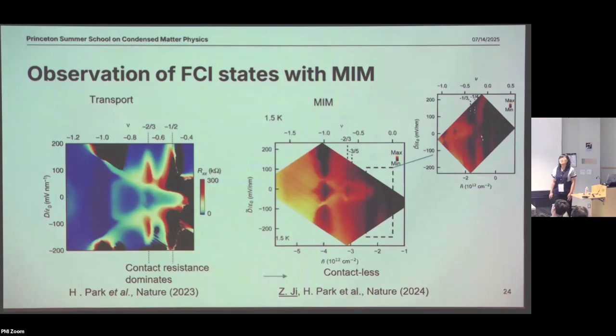So we did a lot of engineering of the top gate, because if the top gate is a perfect metal, it screens everything, and microwave cannot go through it at all. Then we cannot get those scanning measurements done. So what we did was use a monolayer TMD as a top gate, and we use excitonic resonance to drive it into the insulating regime, such that its mobility is super small. It doesn't screen microwave that much, but it still has enough carrier density to gate the material to whatever it needs. Then we compared measuring just on the top gate and on the sample. So the top gate is insulating enough that it does not affect this measurement too much.